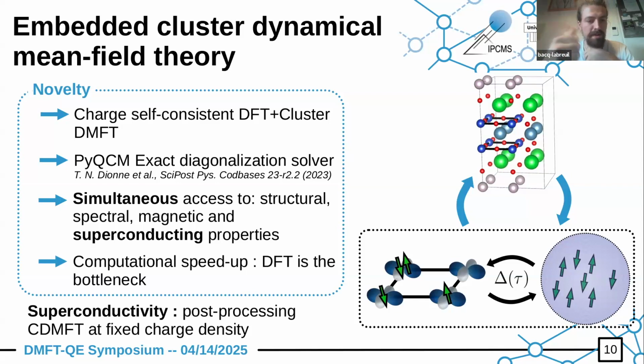And the ED solver also allows us to speed up quite a lot the calculations. And actually, the DMFT part becomes much faster than the DFT part. So DFT becomes the bottleneck. And this is quite important for the study of multilayer cuprates, as I will describe afterwards, because there we deal with quite large crystal structures, up to 100 of atoms. And that's more or less the limit that we can reach at present.